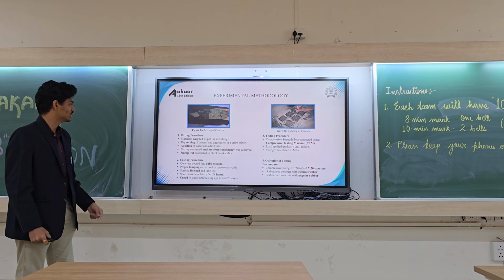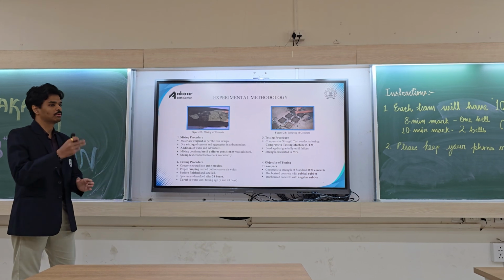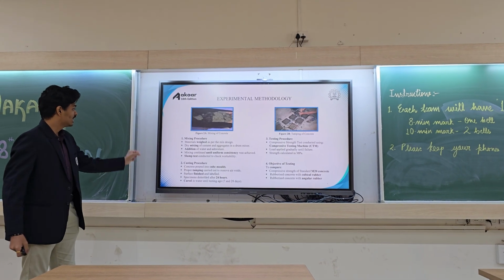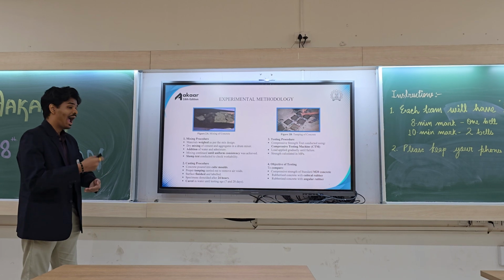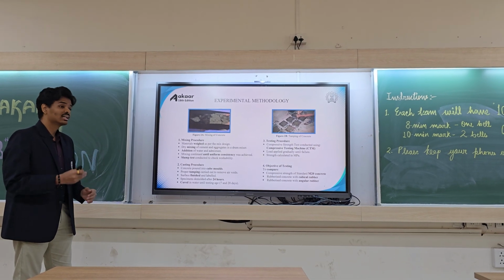So let's begin with the mixing process. Materials were weighed as per mix design as I showed in the earlier slide. Dry mixing of cement and aggregates in a drum mixer, addition of water and admixture. Then mixing continued until uniform consistency was achieved. Then a slump test was conducted to check the workability. Then we cast the concrete. It was poured into cube molds of standard dimensions. Then proper tamping was carried out. Surface was finished and labeled. Specimens were demolded after 24 hours, and then after air curing, they were water cured until the testing age of 7 and 28 days.